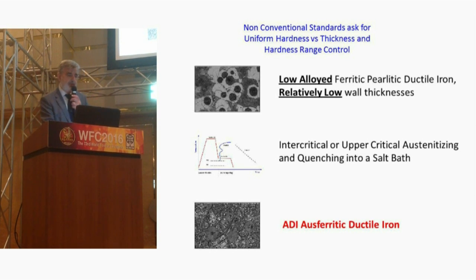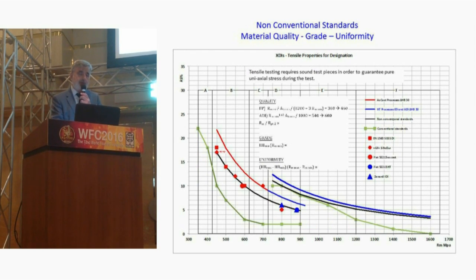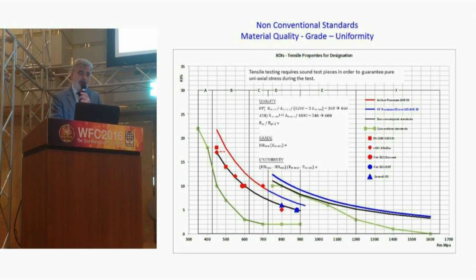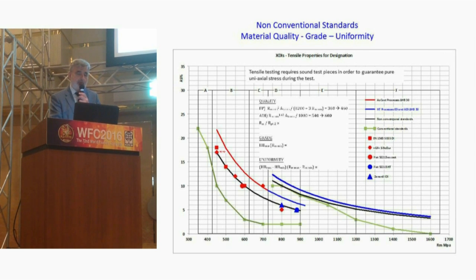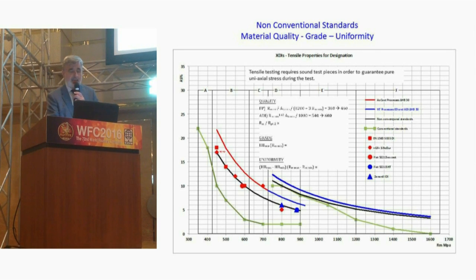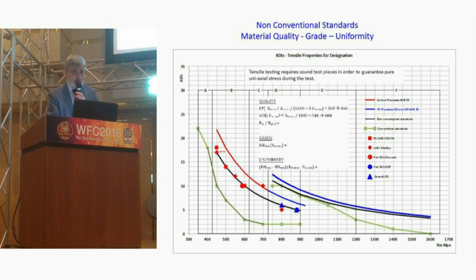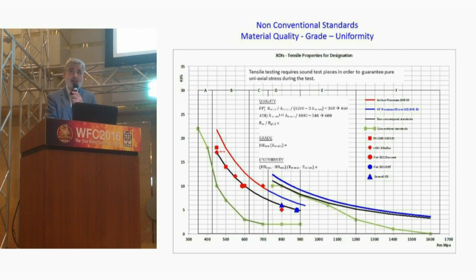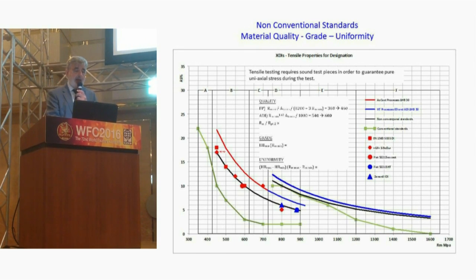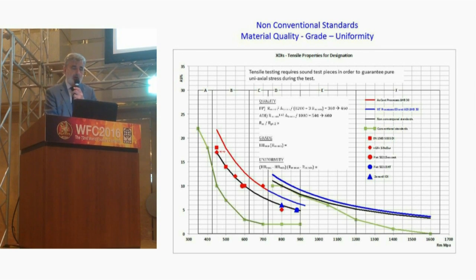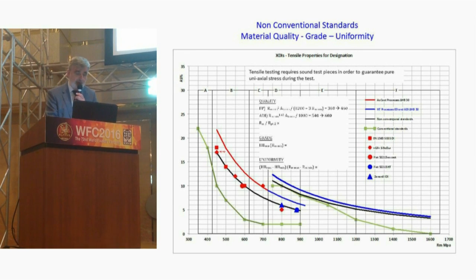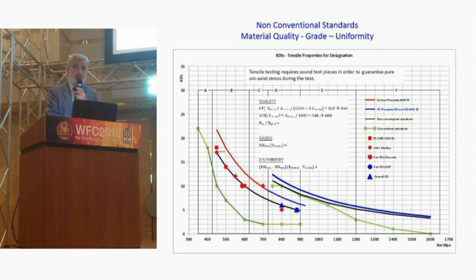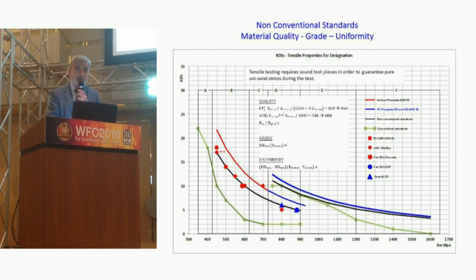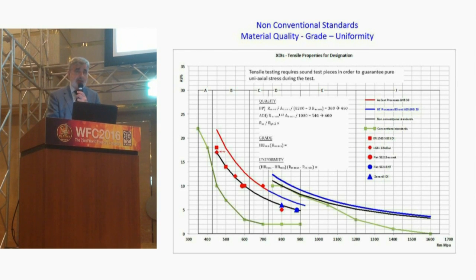These non-conventional standards, you see, can be best fitted with the black line on this diagram, elongation versus ultimate tensile strength. The black lines are one for pearlitic-ferritic grades, and on the right the austenitic, ausferritic grades. The green lines represent the conventional standard that you find in the ISO standard. Of course, when we are talking about non-conventional standards, such as high silicon or SiBoDur or our ADI or Fiat grades, we are obliged to fulfill the requirements of these grades, so that the point represented by A5 and Rm is above the black lines.